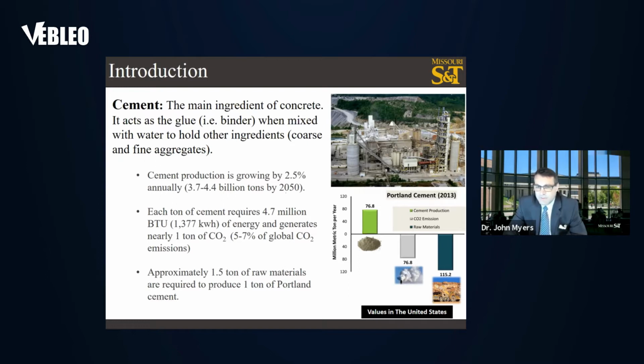There's a large demand for the use of concrete to construct infrastructure buildings, roads, bridges, and dams, and this has increased tremendously. Cement production is growing by 2.5% annually and is expected to reach 3.7 to 4.4 billion tons by 2050. However, cement production is also a key source of CO2 emission due to the extreme heat required to produce it. And as you can see here, each ton of cement requires 4.7 million BTU of energy and generates nearly 1 ton of CO2 emissions. And this is actually between 5 to 7% of global CO2 emissions.